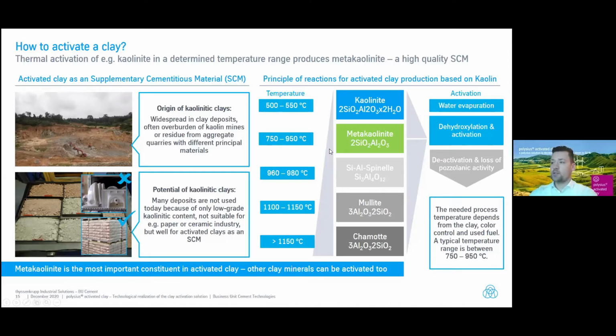What is very important to know is that we don't want to overheat the metakaolinite. Because if you overheat it, for example, in some rotary kilns, this can happen, then you will form some other phases which are not active anymore. So you are destroying the activation and you will come up with a very low product quality. And this is not our target. Our target is to produce the best quality activated clay out of your available raw clay. This is our target.